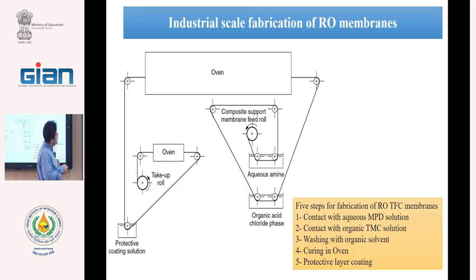Next, this roll acts as a plastic rubber and removes the excess MPD solution, and in the second bath it goes to the organic acid chloride phase, that is TMC dissolved in hexane, heptane, or organic solvents. The reaction happens, a thin layer coats the support, and after the coating, it goes to an oven for completing the reaction and for drying. After that, in lab scale, we finish the membrane fabrication in this step.